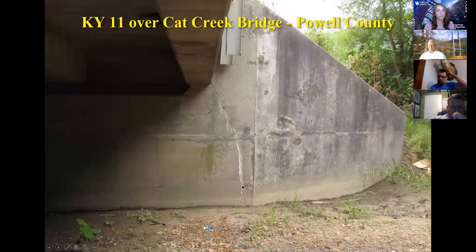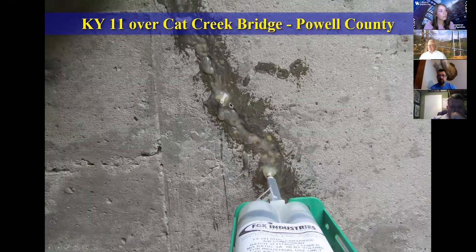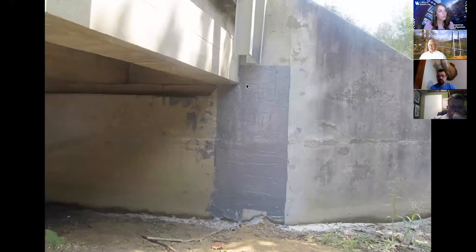Now, we don't only repair beams, we also repair abutment walls. This was a crack in the abutment wall. Again, the steps are to fill the cracks, and then we apply the fabric on it. And basically that holds the crack from growing on this side. It's very difficult, of course, for us to go back to the back side of it.